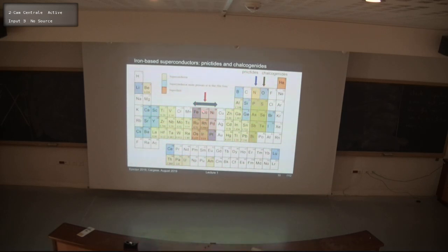And we have a lot of degrees of doping, so if you replace iron with cobalt, you donate an electron. If you replace iron with nickel, you donate 2 electrons. Sometimes also ruthenium and rhodium are used for doping effects. So these are all part of 3d transition metal ions, where often we have very rich physics coming from the fact that we might have strong correlation as well, and we have Hund's coupling and other effects playing a role.